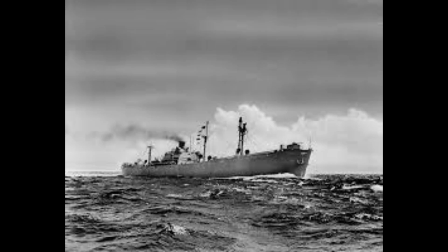The report stated that plates from Liberty ships, which had experienced brittle failures, had transition temperatures ranging from 15 to 65 degrees Celsius, with a mean of 40 degrees Celsius. This steel would be notch brittle during winter and spring in the North Atlantic. The specifications in use had not been sufficiently selective to exclude such steel.